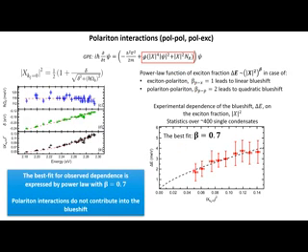So we put all this data here, and then we tried to fit it with different functions, and the best fit resulted in beta equals 0.7 for the power law of exciton fraction. Therefore, from here we can conclude that it is very unlikely that polariton interactions in general contribute to the process, because one should expect a superlinear or at least linear dependence, but not sublinear, of course.